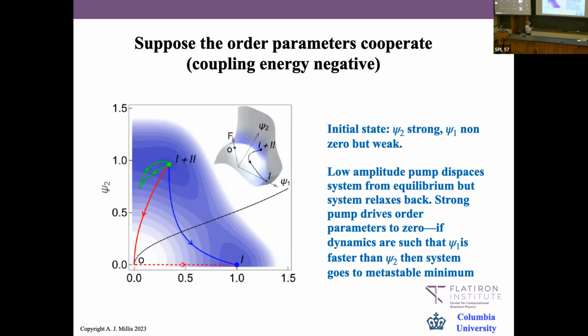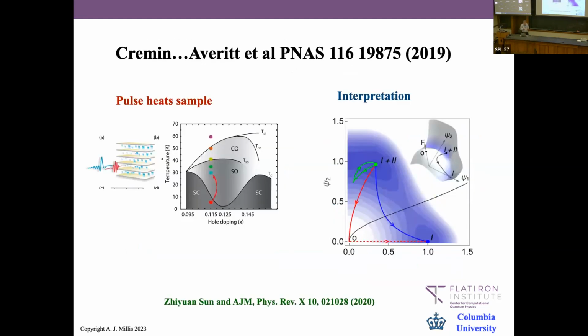For a very strong pulse, you go all the way to the origin, then relax to the wrong minimum. For an intermediate pulse, you can kind of skim around the edge. So this scenario, I think, is what's going on in the superconducting experiments that I showed you.